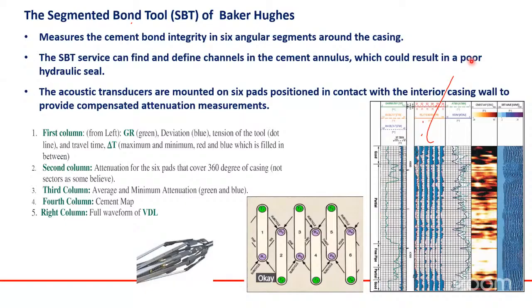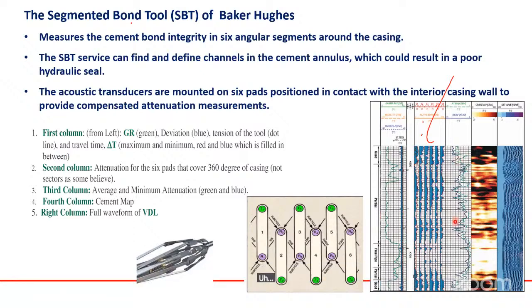Which result in a poor hydraulic seal. The acoustic transducers are mounted in a 6-pad position in contact with the interior casing wall to provide compensated attenuation measurements. So we have six curves instead of one, and we have minimum and maximum amplitude. If these are the same, it means we have good cement, and if there is a difference between them, we have a channel in the casing. It can also provide a cement map in addition to the VDL.